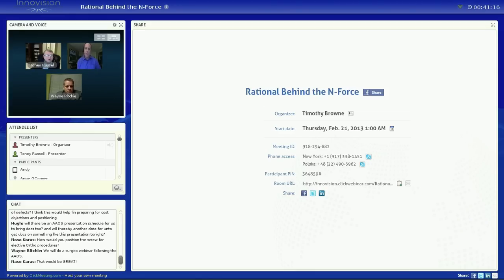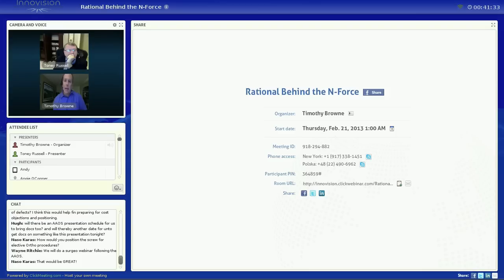Tony, would you like to address the question about using beta versus CarriGen, or would you like me to field that? Go ahead. So you all know, Dr. Russell just explained that the FDA cleared both beta and CarriGen. Beta, as you all know, has 30 megapascals of compressive strength, where CarriGen has around 10 megapascals. So obviously, in these defect situations, it would be better to use the higher compressive strength material. The other benefit of beta is that it has the syringe-to-syringe mixing system, which makes it way more convenient. Currently, with CarriGen, you've got to mix it in the bowl, stuff it into a 1 cc syringe and inject, then stuff some more into a syringe and inject. So we know that ETEX is working on an initiative right now for a different mixing system.